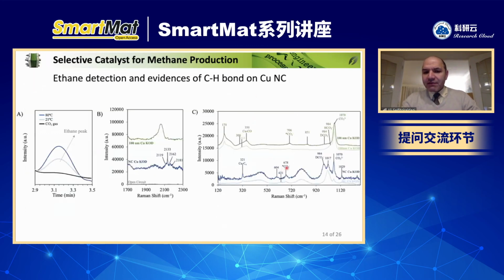And then our IR, we didn't run the time resolved kind of Raman or IR. We didn't have that sensitive IR in our lab, but we performed Raman with different isotopes. Sorry, I forgot the terminology. Instead of using the KOH, we use the KOD, the marked hydrogen to show the shift to ensure that the carbon products is in fact coming from the CO2, not coming from any other sources.